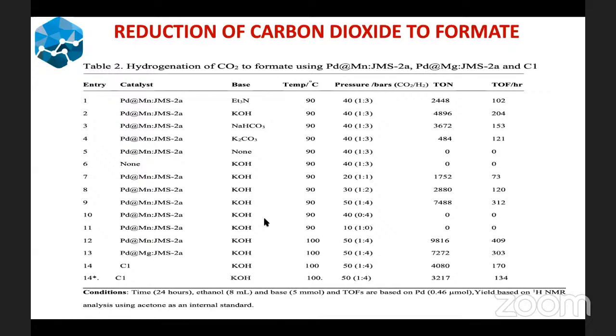Okay, so we also varied the pressure, and as we vary pressure, you can see that in the presence of KOH as a base, the yield of the formate that is formed also increases. We also changed the temperature from 90 to 100, and again in a pressure ratio of 1:4, that is your carbon dioxide to hydrogen, and we obtained a turnover number of 9816 with a turnover frequency of 409.